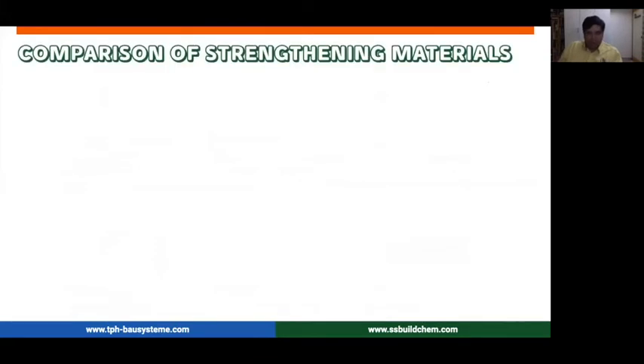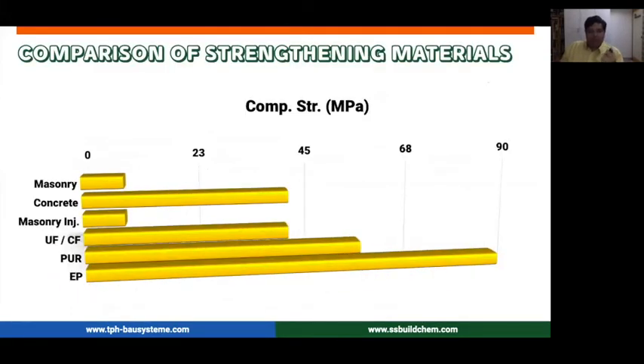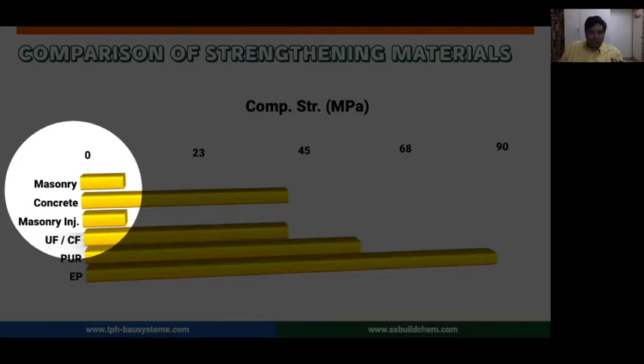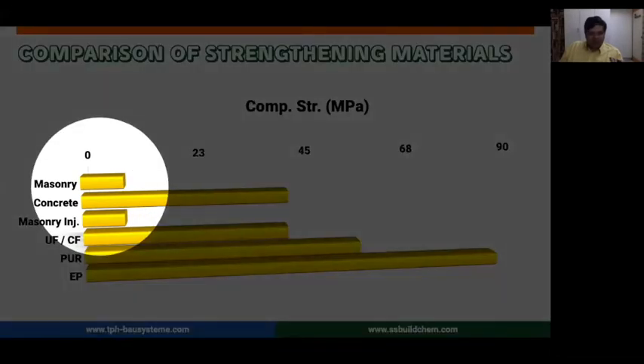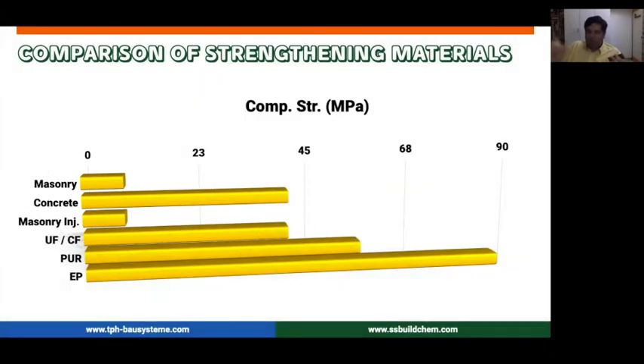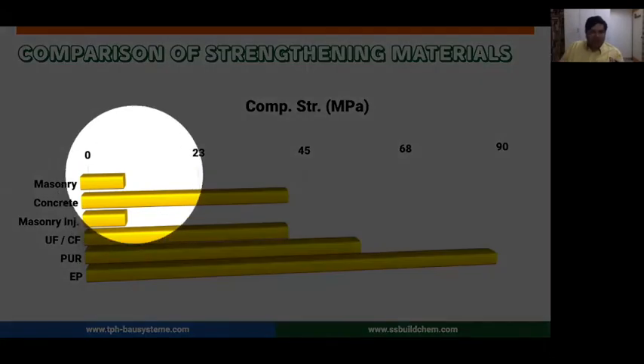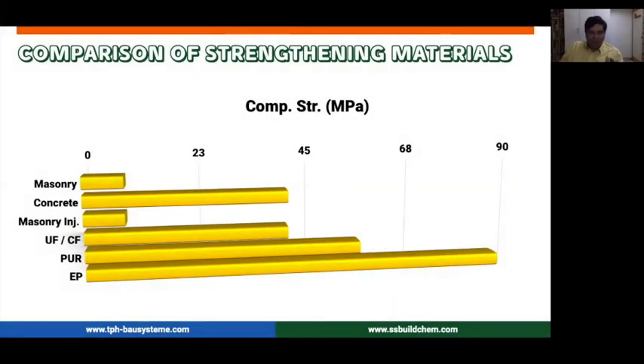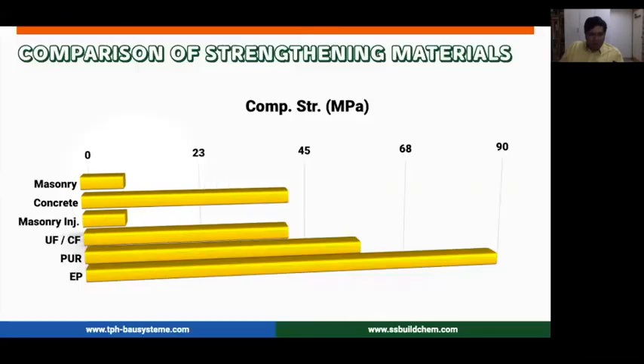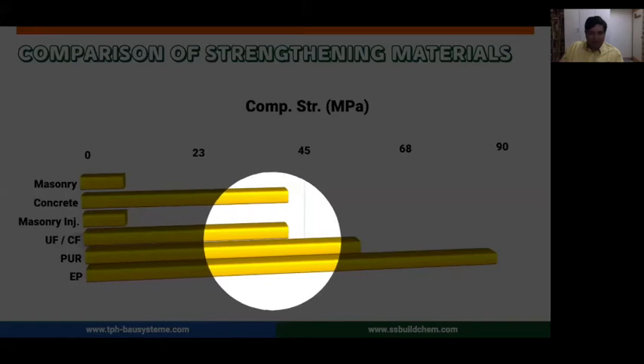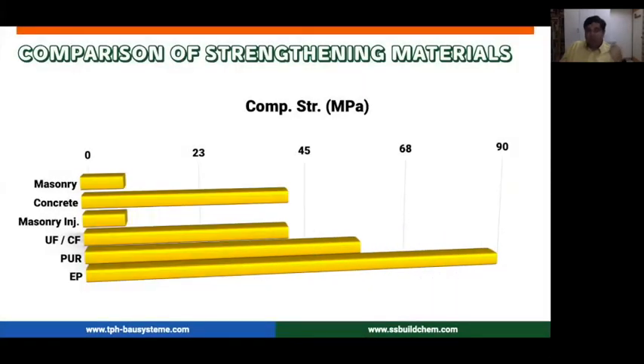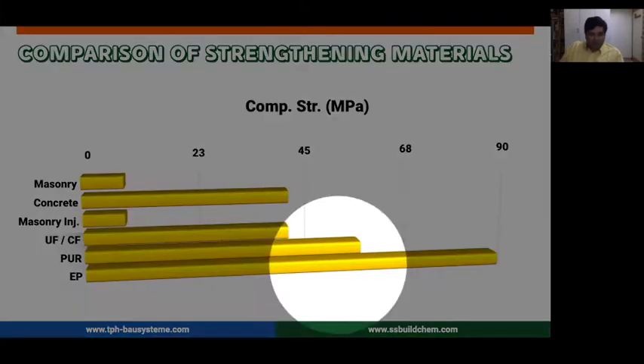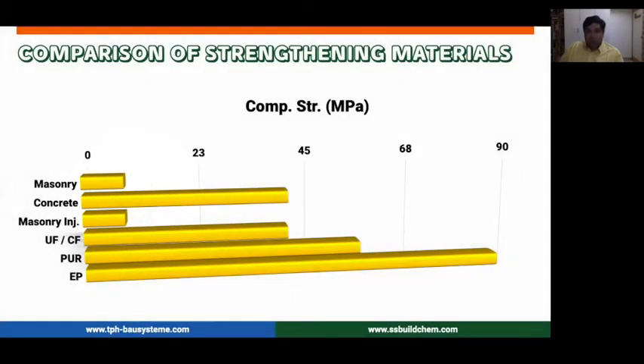Now this is another parameter which you have to understand very well. For example, we can think about repairing two kinds of structures, masonry structures or concrete structures. We can say the average masonry has a strength of only about 8 to 10 MPa, somewhere thereabouts. The average concrete is somewhere around 40-45 MPa. So any injection system that we select has to fit into these values. For concrete you can use cement-based materials, PU or epoxy materials, because they really allow the transfer of load across the cracks. But if you are trying to treat a masonry structure, then it is better to use a very low strength material.